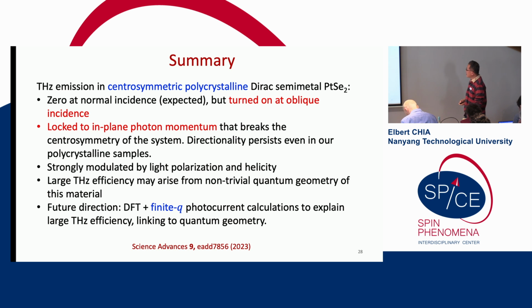So this is my summary: we can get very large Terahertz emission from this centrosymmetric material, which is polycrystalline. It is locked to the in-plane photon momentum, and the large Terahertz efficiency may arise from a non-trivial quantum geometry. And this point about polycrystalline is quite important because a lot of the time we think that we need something that's super high purity, single crystal, but yet in this polycrystalline thin film that we have, we already get a very large Terahertz emission. So the future direction would be to perform DFT and to perform a finite Q photocurrent calculation.